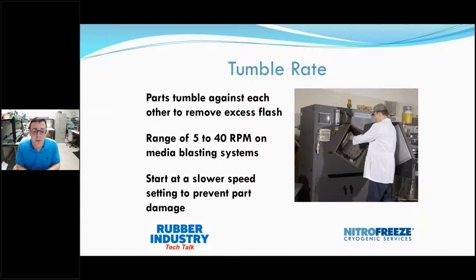Next, we have tumble rate. That is essentially the basket tumbling, with the parts at the bottom of the basket tumbling against one another. That tumbling function is largely what removes the external flash from the component being processed. This range is anywhere from 5 to 40 RPM. With a cryogenic tumbler, it's usually lower.